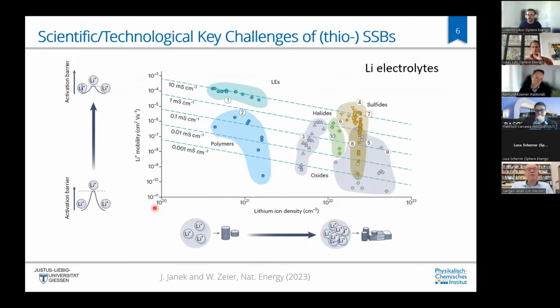What you see here is a typical picture shown in the semiconductor industry: lithium-ion mobility as a function of lithium-ion charge carrier density, so concentration, and the product is conductivity. So these lines are isoconductivity lines. The highest conductivities, about 10 millisiemens per centimeter total conductivity, have, of course, liquid electrolytes and the sulfides, the ceramic materials, but at the cost of a factor of 20 higher lithium concentration, then 30 to 35 volume% of the battery. So this is, of course, when it comes to resources, maybe an issue.